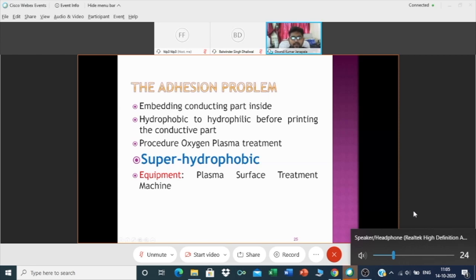If you are not activating your polymer, you can simply embed your conducting part inside your polymer and put another polymer layer and cure it. So your conducting part will be inside of your polymer like an encapsulation. That is one way to do your fabrication using flexible antennas. But if you want to coat on top of the PDMS, then you need to activate your polymer, hydrophobic to hydrophilic. Basically, hydrophobic means something that will not react with water. If you put a water drop on top of it, it will not have any reaction with that one. It will stay like a bubble, parabolic bubble.